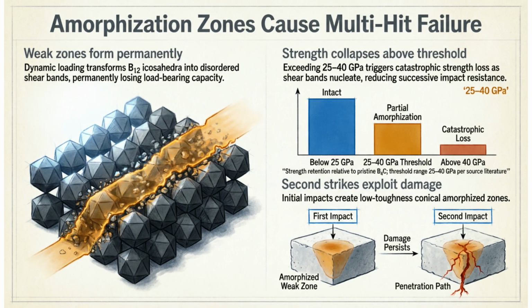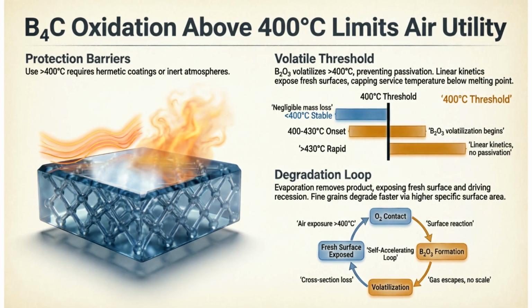These amorphized zones are permanent, creating weak points in the material. Subsequent impacts can exploit this damage, further reducing the overall resistance of the armor. Environmental utility is also constrained. At temperatures above 400 degrees Celsius, oxidation occurs as boron trioxide volatilizes, preventing effective surface passivation.